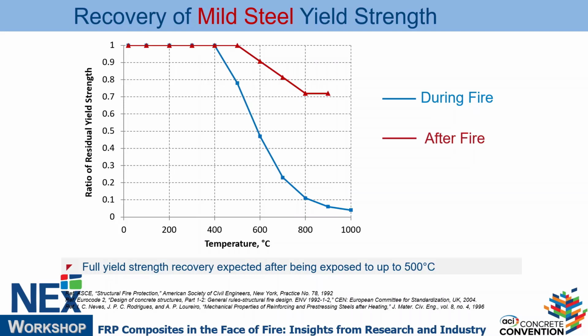So during fire it drops. When it cools down, it gains back strength, right? Actually, there are some curves for concrete. Even concrete, when it cools down, sometimes it gains back some strength, and it actually hydrates again, starts absorbing moisture from the air, and there is a gain in strength. But that takes a year to happen. Most of the time, if there's damage, you start on it immediately. So nobody's going to wait a year to figure out how much the concrete will gain. Immediately start chipping back concrete and doing repair and strengthening.